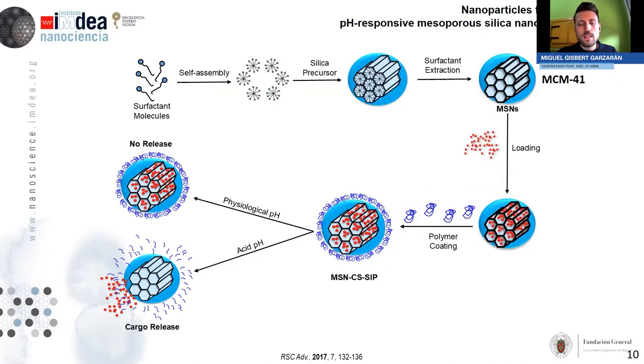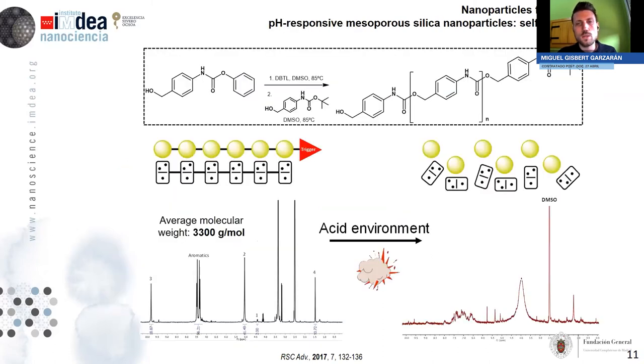Okay, so in the first example that I'm going to talk about, we focused on designing MCM41 mesoporous silica nanoparticles engineered with a pH-responsive self-immolative polymer. So the objective here was to verify that this self-immolative technology was actually a good way to prevent premature drug release and allow it only inside the cells. Okay, so for this gatekeeper, we employed this polymer that you are seeing now. So this is a self-immolative polyurethane that is based on aminobenzyl alcohol. In the absence of an acid environment, it has an average molecular weight of around 3K. But when we subjected it to an acid environment, we can see that the structure is completely lost. So in fact, we have a polymer that is degrading in the presence of an acid environment.